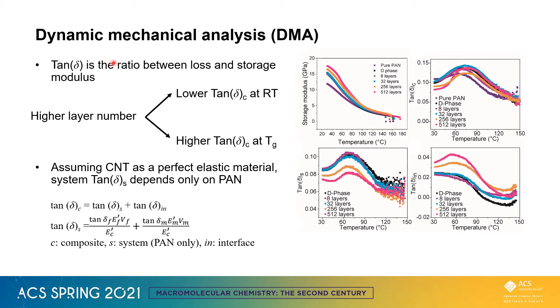We also used dynamic mechanical analysis to show the interfaces between each layer. At room temperature, the 512-layer fiber showed the lowest tan delta, meaning that the polymer chain has the lowest mobility. But at temperatures beyond its glass transition temperature, the 512-layer fiber showed higher energy absorbance. We further dissected the tan delta into system and interface contributions, and observed that 512 layers with more layers have more interface.